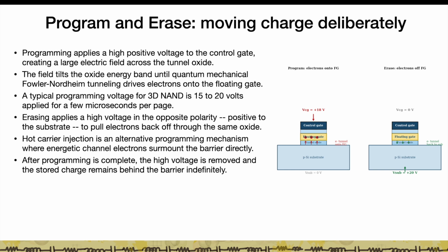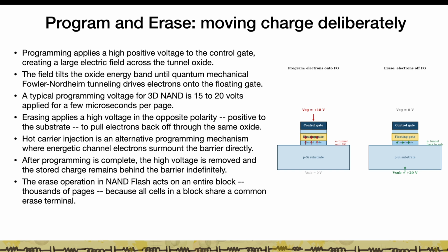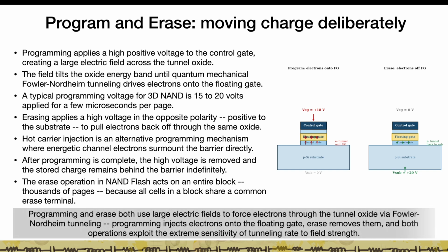The critical point here is that both operations use the same oxide and the same tunneling mechanism. Programming and erase are not two different physical processes. They are the same Fowler-Nordheim tunneling, driven in opposite directions by opposite polarity fields.